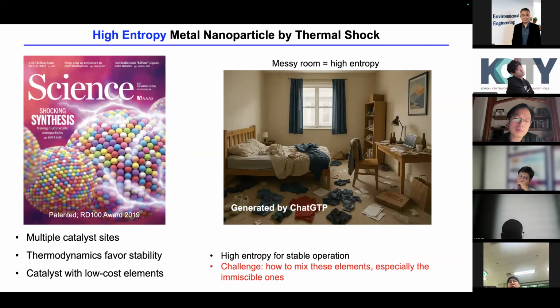So one of the major challenges for catalysts, in addition to using low-cost elements, is the stability, right? And one of the key concepts here is high entropy. Basically, it means if you have a random system, a disordered system, like the bedroom on the right side, it's very stable, right? If you don't put energy in to organize them, this randomness is going to be here for a very long time. And so the idea here is, how can we use this high entropy concept, having a lot of elements, and you randomly mix them into a particle, and thermodynamically, you can use the high entropy concept to stabilize the catalyst. And now you not only get a low-cost catalyst, but also they can perform with very good stability.